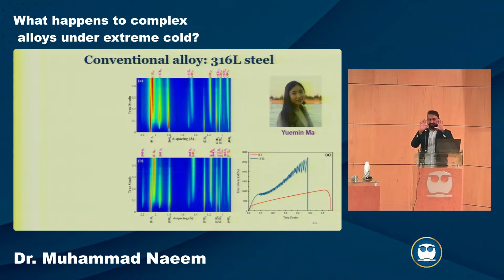You remember, like I mentioned, that one is for loading, one is normal to that. In this case, I have shown the previous example where the same peaks were changing, but there were no new peaks. But here you see that, for example, over here, I don't know if you can see my pointer, I think you cannot. But you see some new peaks are coming, right? For example, after around 2 angstrom or so, there are these new peaks. Then another one appearing over here.